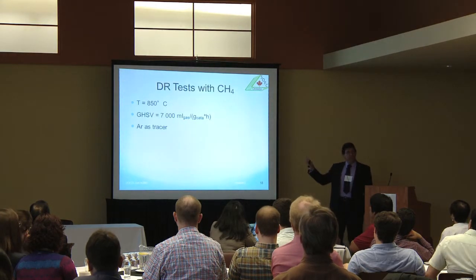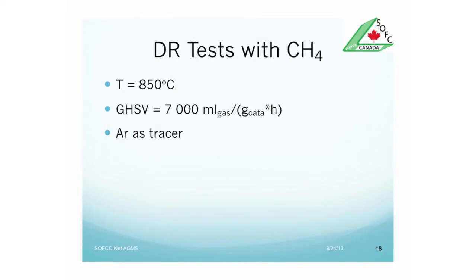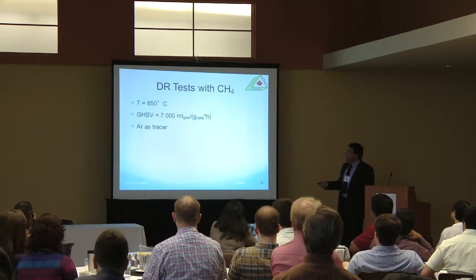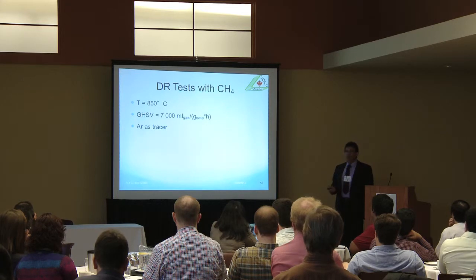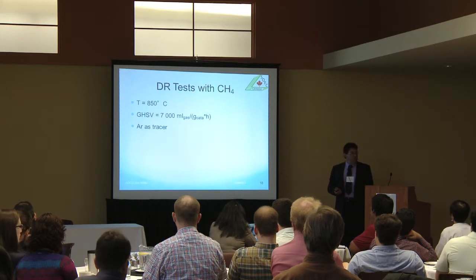So these are very new results, not belonging to this network because they were obtained after the end of the network. We have done some work testing the catalyst at a gas hourly space velocity of 7000, almost double, and using argon as a tracer for dry reforming of methane, which is even more difficult to reform than diesel.